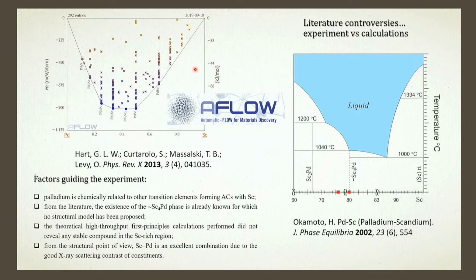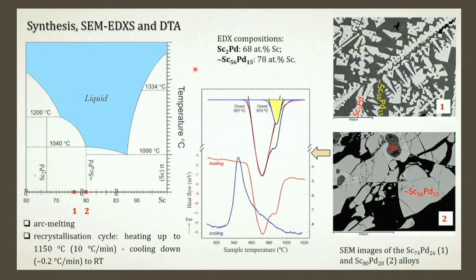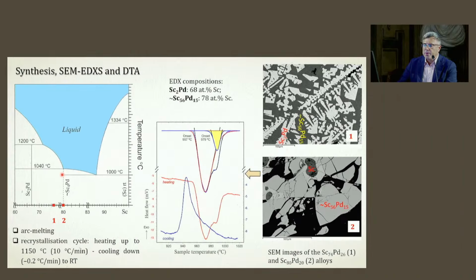So we decided to make a synthesis. It was enough to prepare just 2 samples by arc melting to confirm that this compound exists, and the average composition is close to 56-15, and the temperature of formation is also similar to what was published in literature.